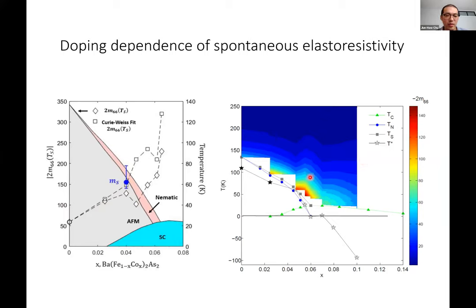So, using this correspondence I mentioned before, we now re-examine these elastoresistivity measurements, and you can see that the value of the elastoresistivity coefficient at the transition temperature actually increases quite a lot as you reach the quantum critical point. So that basically means that the spontaneous elastoresistivity coefficient is also increasing by the same amount, if the mean field framework works until you reach the quantum critical point.